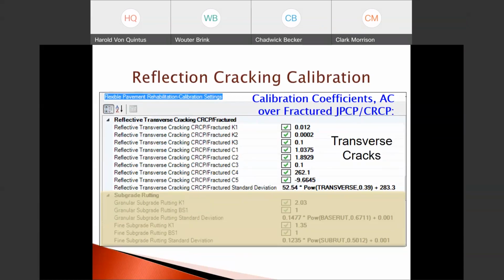This now shows the calibration coefficient screens of AC over fractured jointed plain concrete and or CRCP. Some of these only have transverse crack calibration coefficients because bottom-up fatigue cracks in the asphalt overlay are assumed not to occur. That does not mean top-down fatigue cracks do not occur. They do occur, and they are predicted in the Pavement ME software for these different rehabilitation design strategies, but those are not reflection cracks. The calibration coefficients for fatigue and transverse are only for bottom-up fatigue in the existing AC layer and or transverse cracks in the existing AC layer itself.